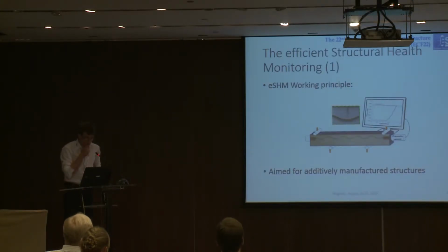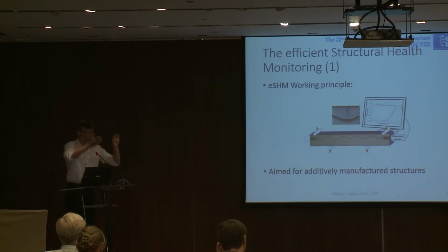In my lab, we are working on a specific implementation that we call the ESHM. The working principle is very simple. I will explain it on a lab example, which is a rectangular beam under a four-point bending test with cyclic loading. What you want is to be warned when a fatigue crack develops in that beam. To do that, you include inside that beam a void, or actually, since that's a bit long, let's say a gallery. This gallery is enclosed, meaning there is no contact with the atmosphere. And before the test starts, you put a different pressure in that gallery.